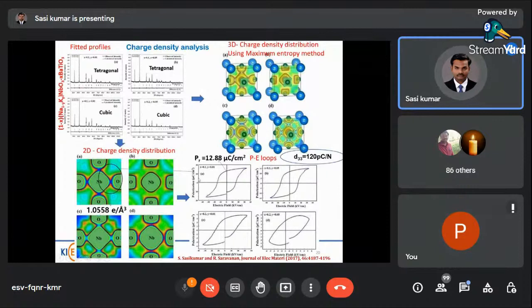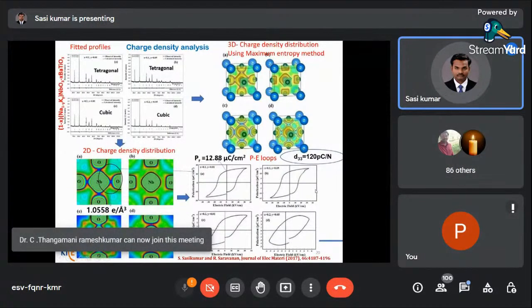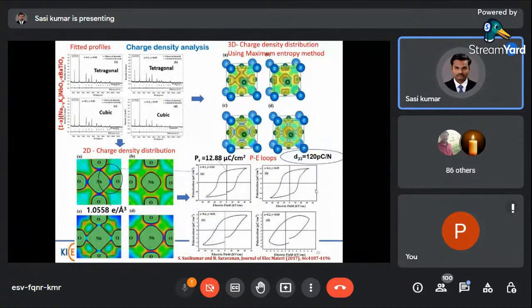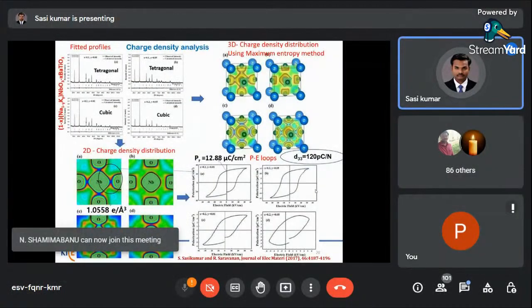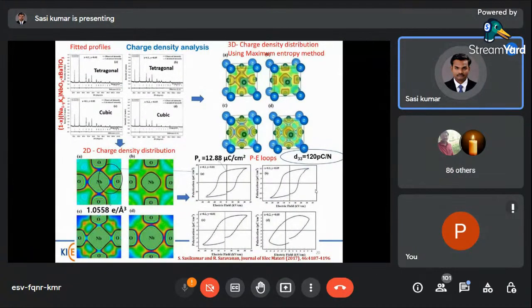Here I can correlate the charge density, the mid-bond electron density, to the ferroelectric and piezoelectric properties. The higher amount of charge accumulation between the titanium, niobium and oxygen atoms gives more vibrations in that composition, so it has higher polarization values compared to other compositions, and it has higher D33 values. A D33 value of 120 picocoulomb per Newton is observed for the x equal to 0.1 composition.